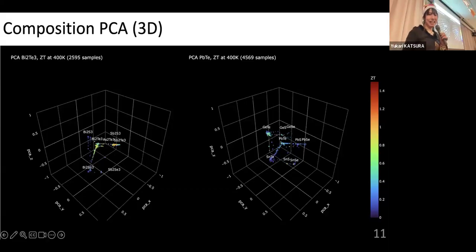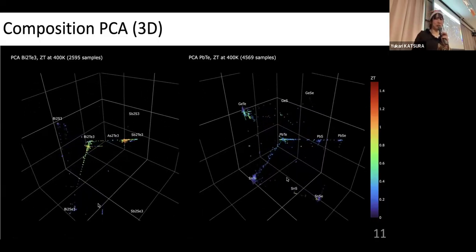Okay. And another analysis is the composition PCA. PCA is principal component analysis, which is a very basic method in unsupervised machine learning. And by doing this on the composition vector, so I have a list of 100 elements and the fractional composition of each element, and then carry out the PCA on the 100-dimension vector into 3 dimensions, then we can see such geometrical distribution of reported samples.